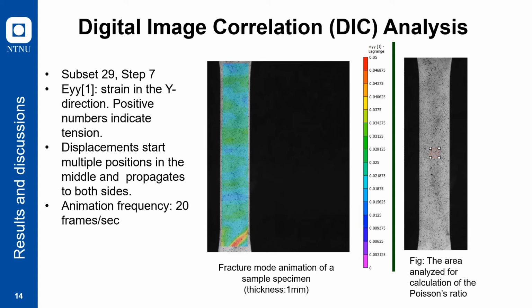And as you can see, the label here, EYY, means the engineering strain along the Y direction. As we play the animation here, as time goes by, there is some deformation in the middle part of the specimen, and it propagates to both sides. Then as it reaches some point, it goes to a different color, which means the strain is getting larger, and then it will have the largest strain showing here, which means this is the area that's most likely to get broken. And these are the methods of calculating Poisson's ratio. For the DIC, we can select one small area somewhere in the middle, and we can do the calculation for the Poisson's ratio.